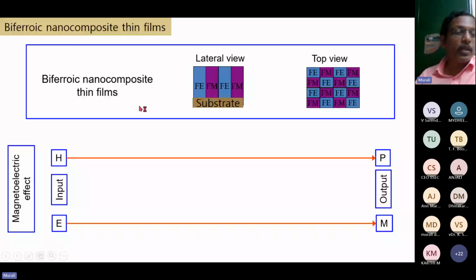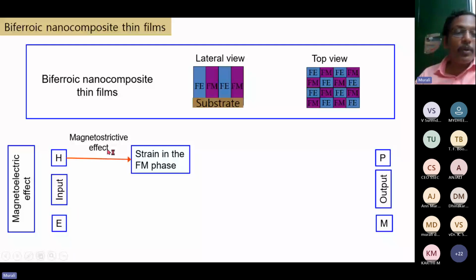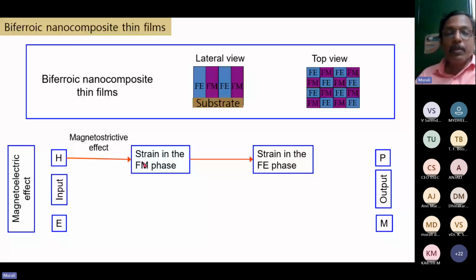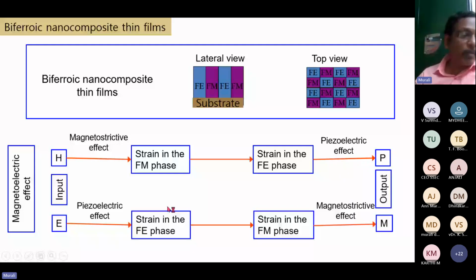Okay, so if we give the input of a magnetic field H, due to the magnetostrictive effect, a strain will be produced in the ferromagnetic phase. This strain will be passed to the ferroelectric phase because these two materials are in contact with each other. So the strain produced in the ferromagnetic layer will be passed to the ferroelectric layer, from which, due to the piezoelectric effect, we can switch the electric polarization. So by applying a magnetic field, we can switch the electric polarization. Similarly, in reverse, by applying an electric field, we can switch the magnetic polarization.